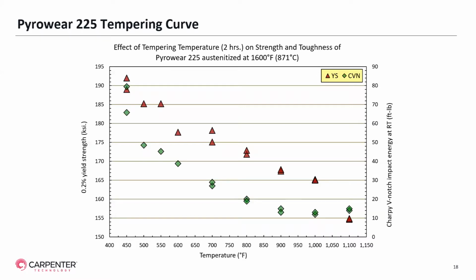So this is a tempering curve for Pyrowear 225. On the left y-axis, I'm plotting the 0.2% offset yield strength. That is given as a red triangle. On the right y-axis, I'm plotting the Charpy V-notch impact energy at room temperature. That's plotted as the green diamonds. And the x-axis shows the tempering temperature.